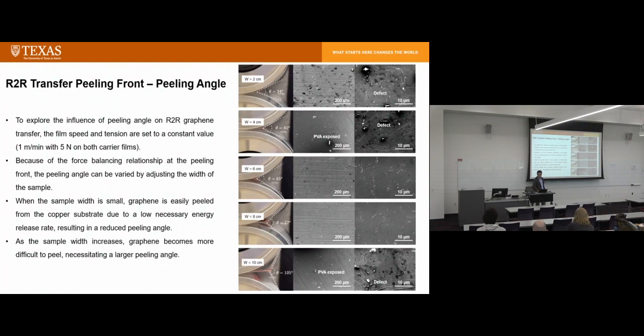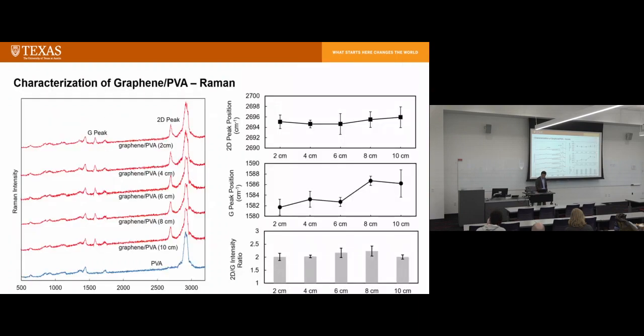And then as the peeling angle increases, we see better quality. At 6 and 8, we see better quality. There are some small features over here, those are graphene boundaries, and those are small compared to those big white dots. And when you have a 10 centimeter width, now you have both defects and also cracks formed in the graphene, because maybe the tension force is quite high. So that's not good for graphene quality either.